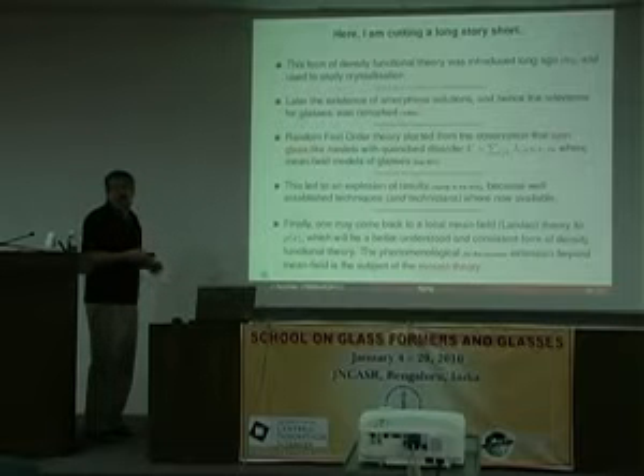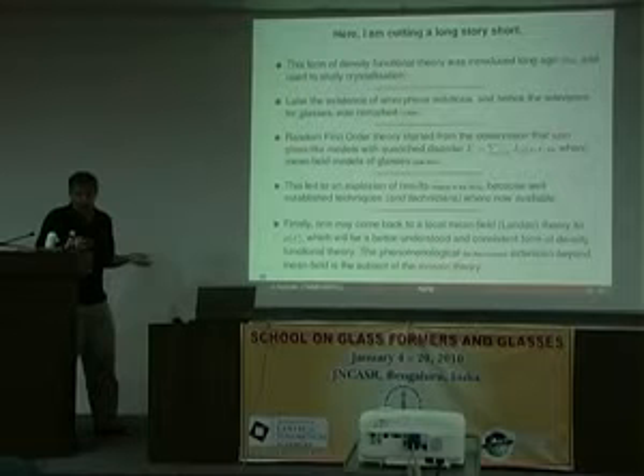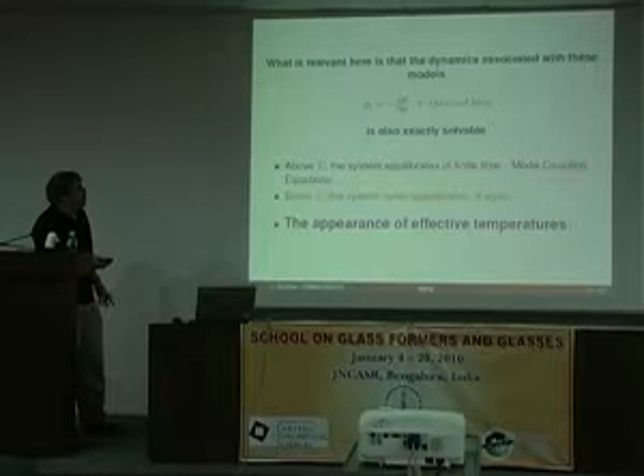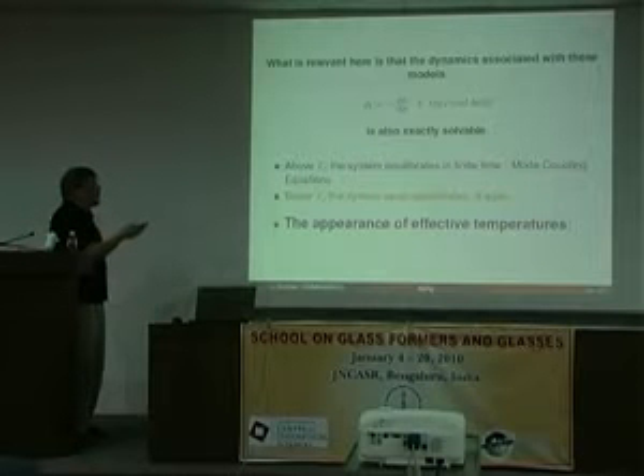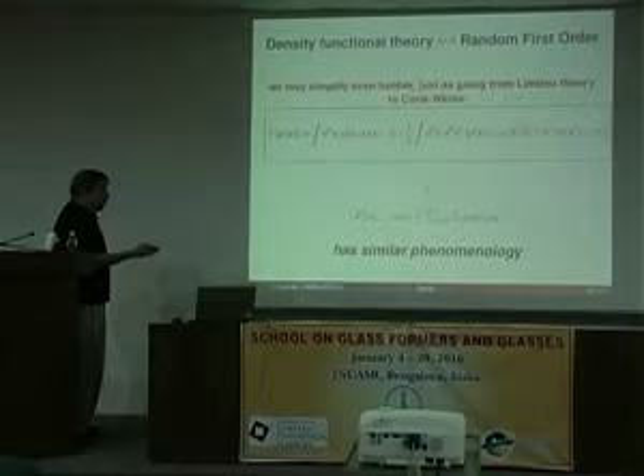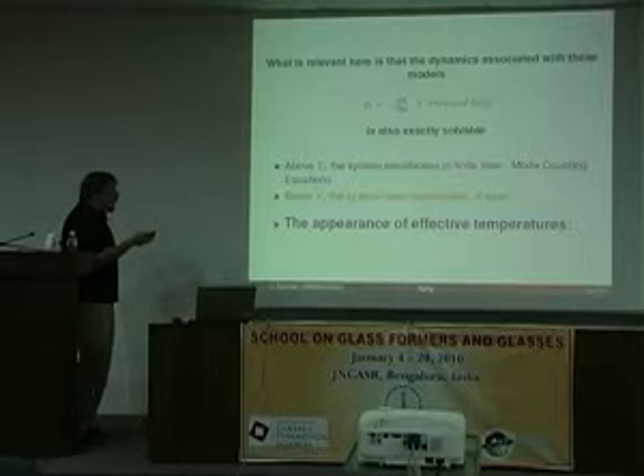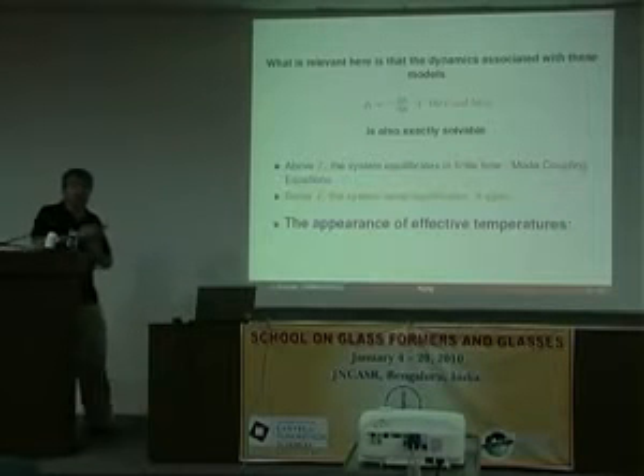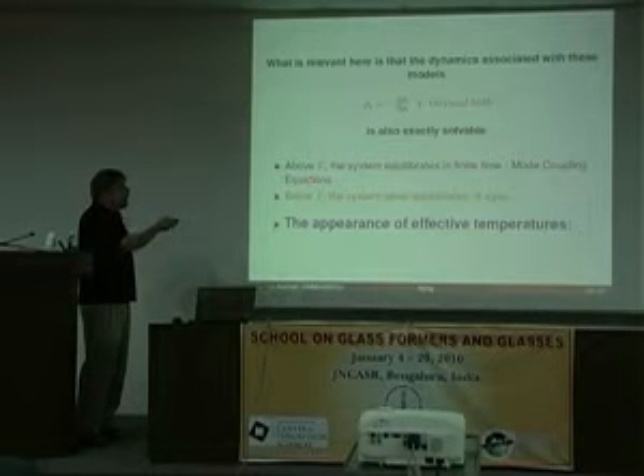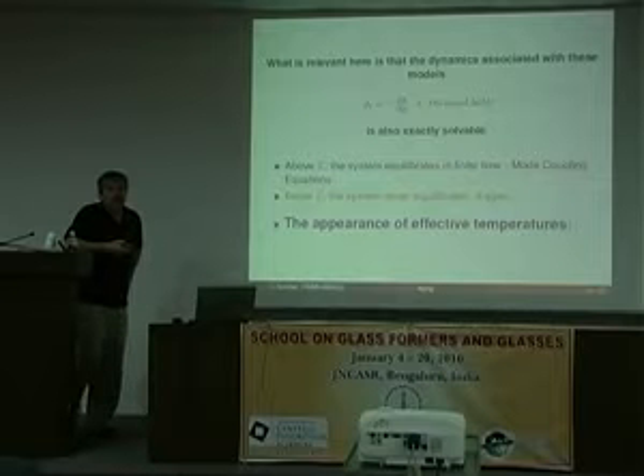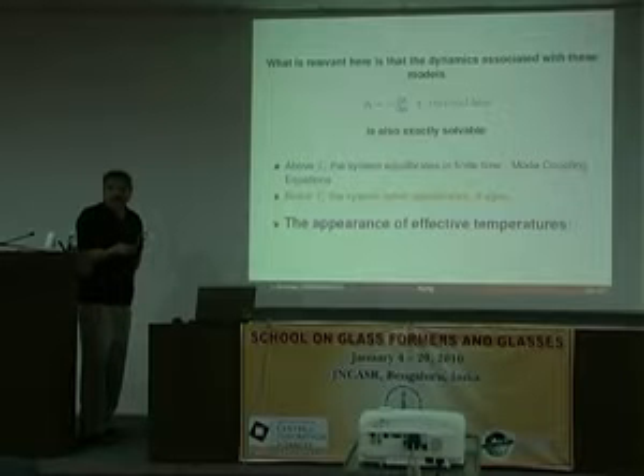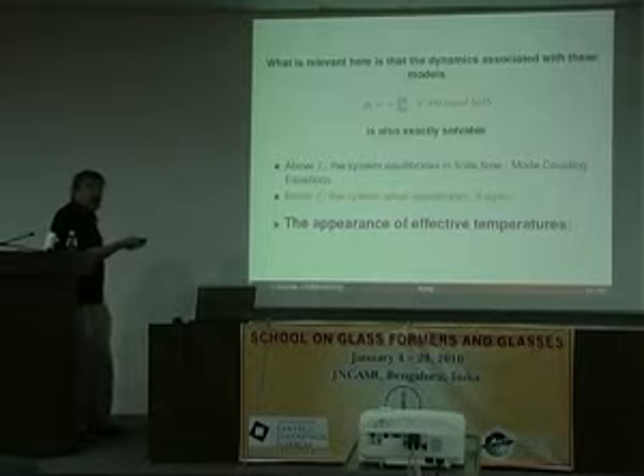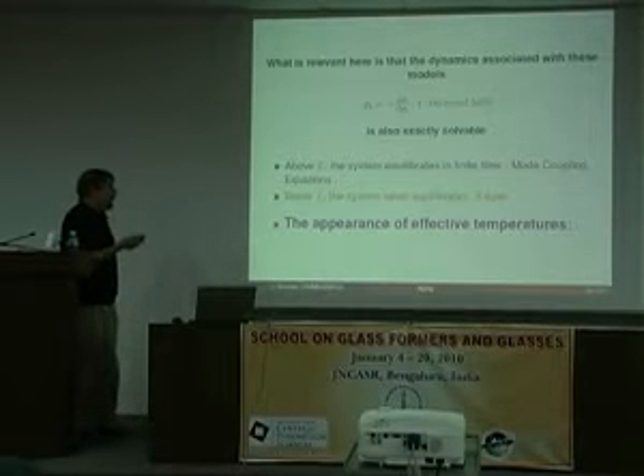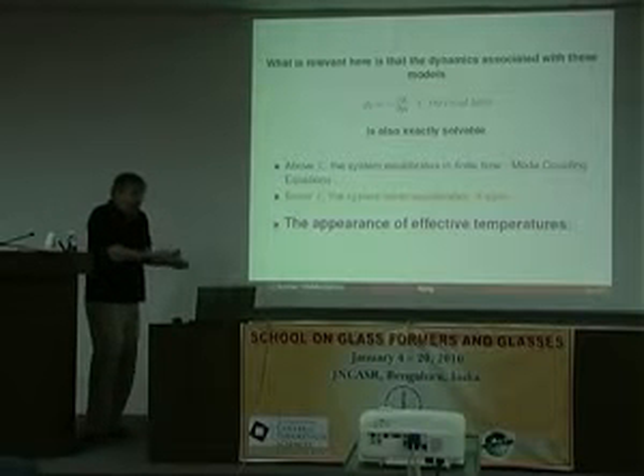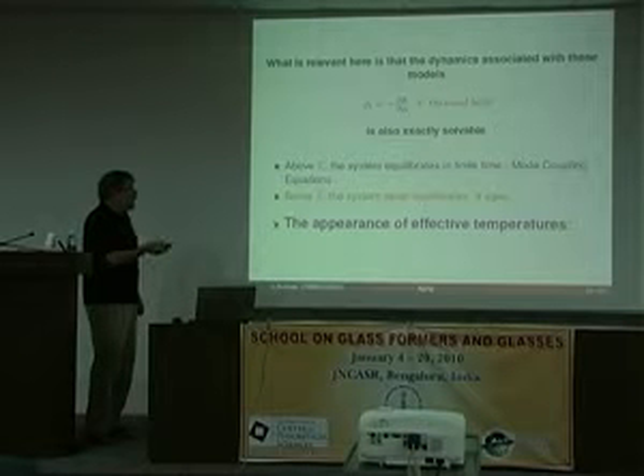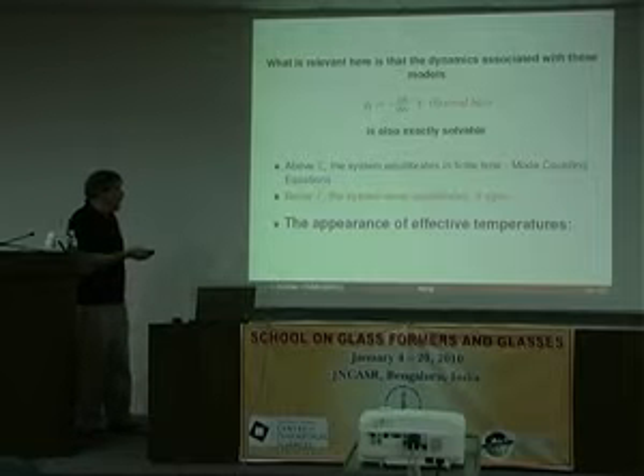So this is a mean field theory. Everybody's interacting with everybody, and people are trying to go beyond mean field painfully and for the moment with semi-phenomenological arguments. What is relevant for us is that you could solve exactly the dynamics associated with this thing. Above Tc, and this was for Kirkpatrick, Thirumalai, and Wolynes, I imagine, a revelation, you get exactly the mode coupling equations, which already existed for the supercooled liquid. Whatever you think of the mode coupling equations, it's a little miracle that they appear exactly and naturally as this. Below Tc, it turns out that you could also solve it analytically. And what you find is that it's not correct to plug in an equilibrium solution because the system never equilibrates. It ages very much like in Struik's experiments.